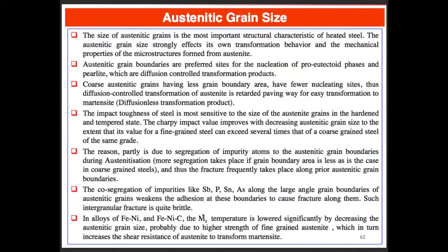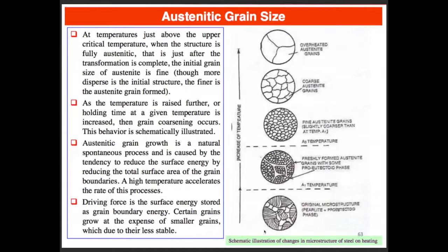We can also affect the martensite start temperature, right, with the decreasing of the austenite grain size. Remember that I talked a lot about the plastic accommodation of the martensitic shear transformation, right? So essentially what we have is a Hall-Petch effect. The smaller the prior austenite grain size, the higher the yield strength, so the harder that martensitic shear is to accommodate, so it stabilizes the martensite, reduces the martensite start temperature, stabilizes the austenite, right?